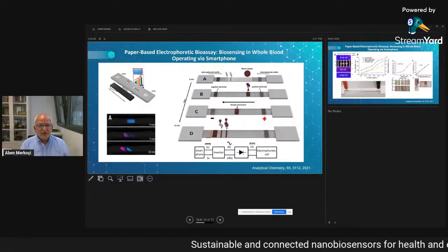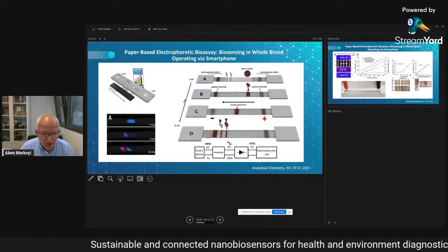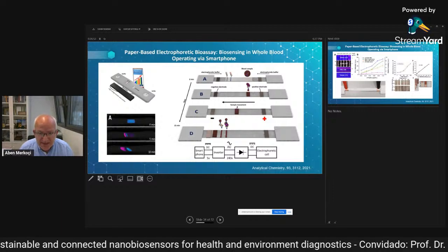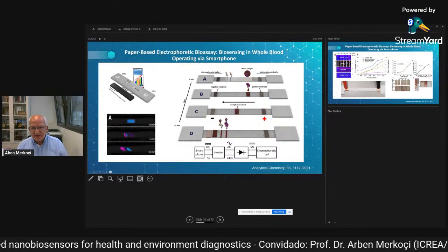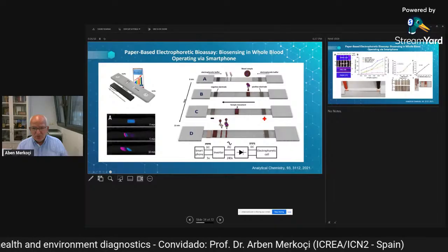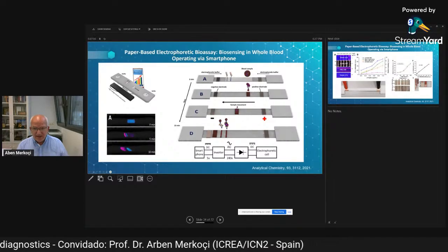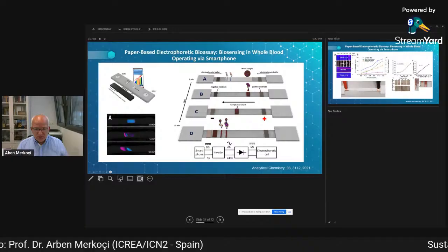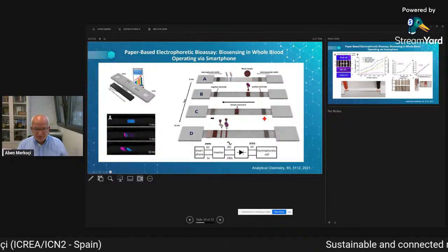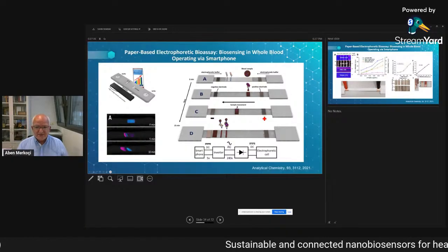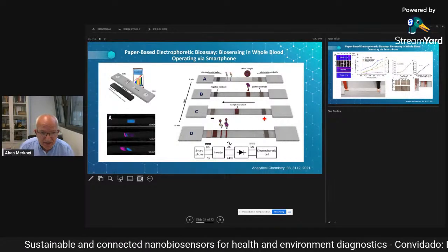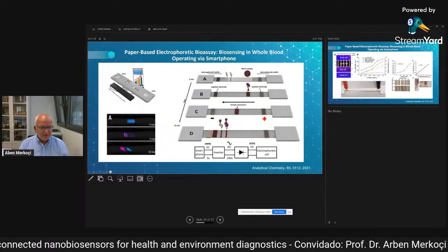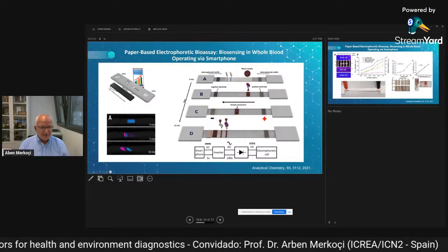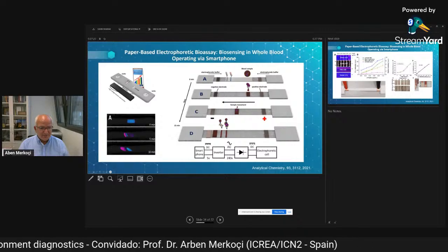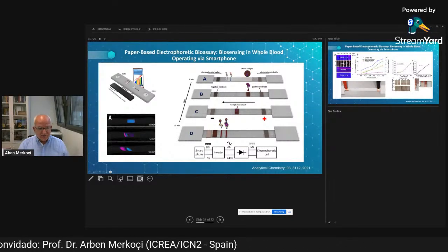Then we have been moving toward improving of lateral flow by combining lateral flow with electrophoresis. And here is the schematic. You see that the lateral flow is connected now to two electrodes, a negative and positive electrode. So by applying the high voltage using a smartphone, using an inverter and electrophoretic cell, we are able to move the sample and boost the separation. We are able to separate the mixture of different quantum dots. You see here blue, and then we have this blue, red, violet quantum dots.